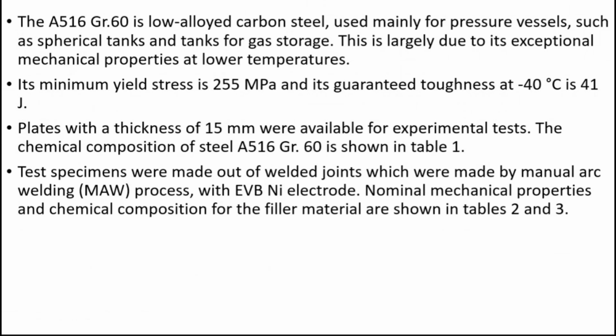Whenever I take data from literature, all mechanical properties are exceptional. I don't know if you notice that as well. So be more realistic. Good one. Actually, the best feature of this steel is that it is cheap, and still it can serve as a good material for many applications. In this case, plates were of thickness of 15 millimeters, and welding was done by the manual arc process with some advanced electrodes, alloyed with nickel.